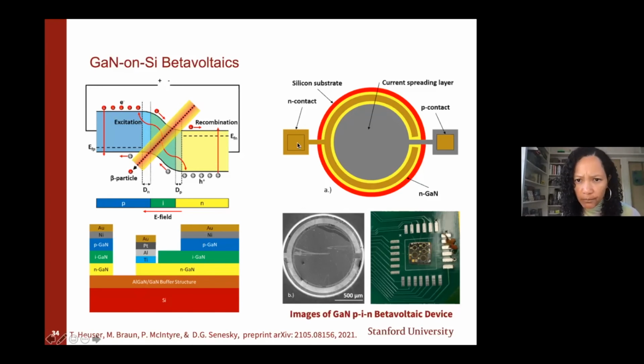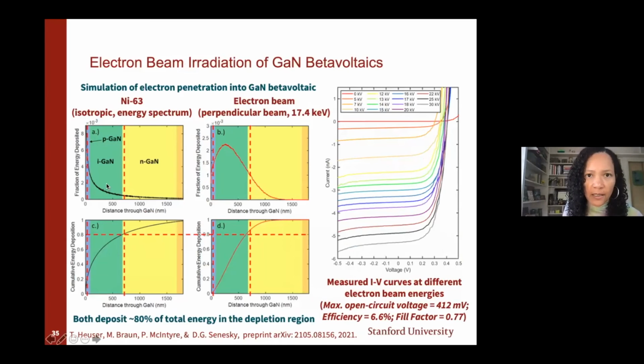But this is the top graphic of our device. We have a current spreading layer with our P contact and then N contact as well. This is a triple mesa etch process successfully made. And Tom Heuser recently did some simulation of nickel-63, which is a radioisotope, and also an electron beam in a common SEM, scanning electron microscope. And what we find is that actually this SEM can serve to have a similar energy profile to an isotropic nickel-63 source.